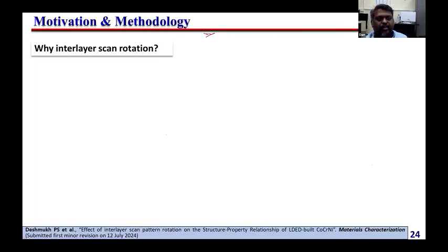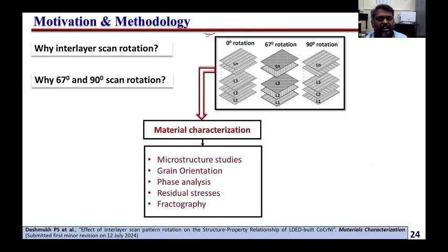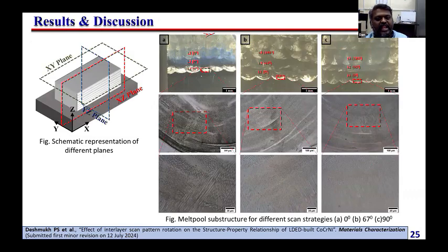Okay, for example, we did it in 3 different conditions. We rotated the scan, which is called interlayer scan rotation. So we used the 67 rotation and 90-degree rotation. Suppose 90-degree rotation means after one deposition, the second deposition will be rotated by 90 degrees. So each deposition will keep on being rotated. In that sense, the cooling rates will change. Basically the thermal gradient will be affected.